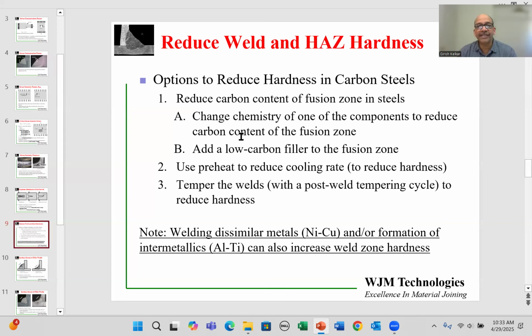If we cannot do any of these, then we sometimes have to resort to preheating. Preheating of the weld reduces the cooling rate. So when you make the weld and it cools down to room temperature, it doesn't cool down very fast, and that helps to reduce the hardness. And if that is not enough, we can do tempering of the welds. The tempering is done with a post-weld tempering cycle to reduce the hardness. Now, many of these topics that I'm mentioning here have already been covered in different videos in the weld metallurgy playlist. So please definitely take a look at those as well.